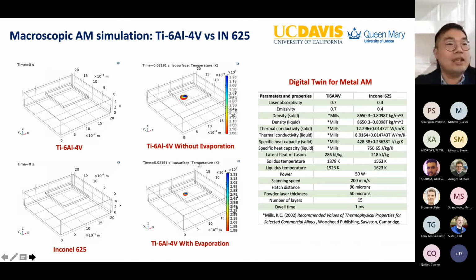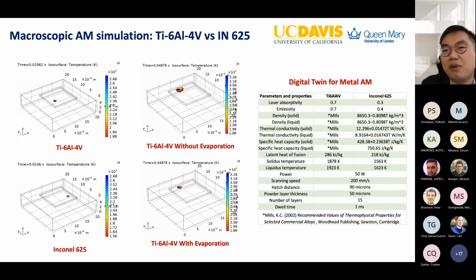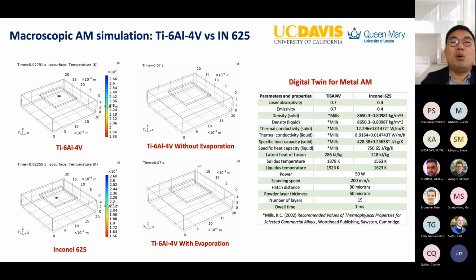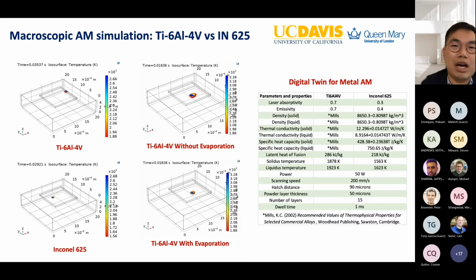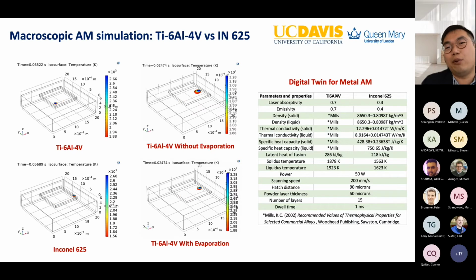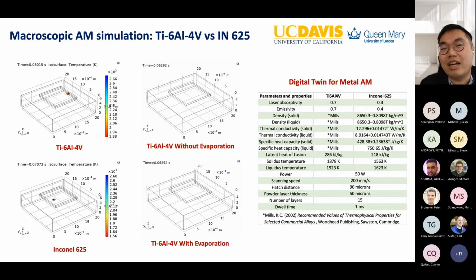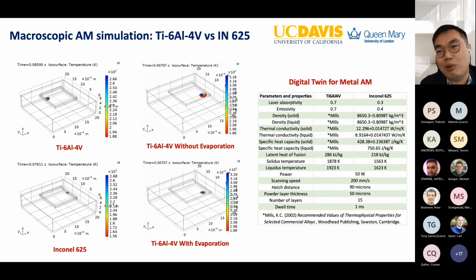And last but not least is how can we make use of all the lower length scale information for the larger length scale analysis. So if we are looking at some material system like Ti-64 or Inconel 625 here, a normal thermal simulation available now hasn't been taking into account much of the lower length scale information. But now we want to develop something called a reduced order model that takes information from the lower length scale into account in order to get the thermal signature right, and later the chemical signature right as well.